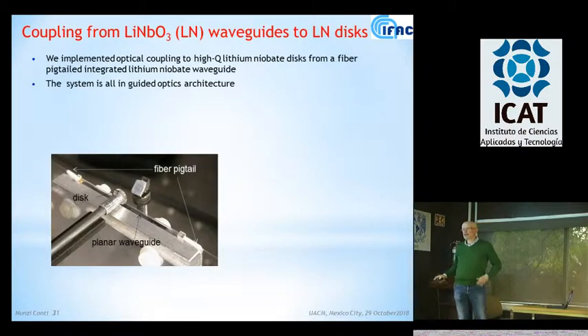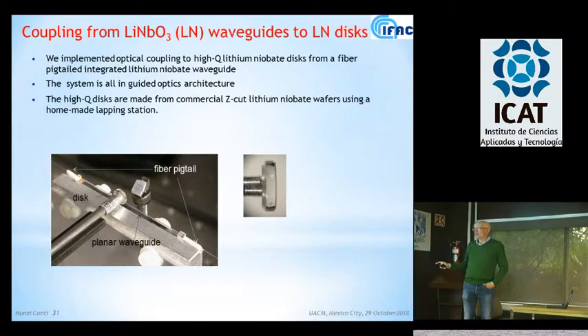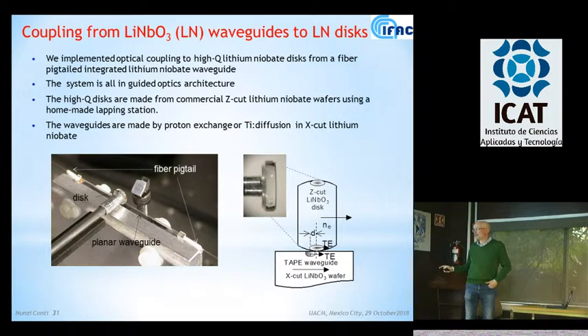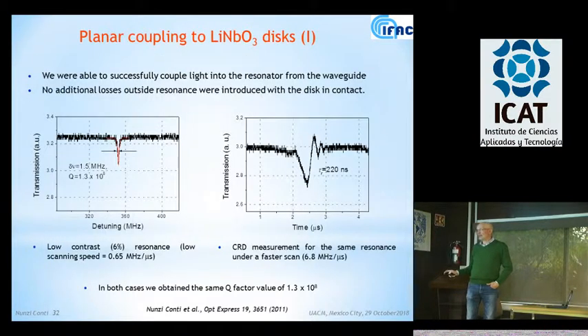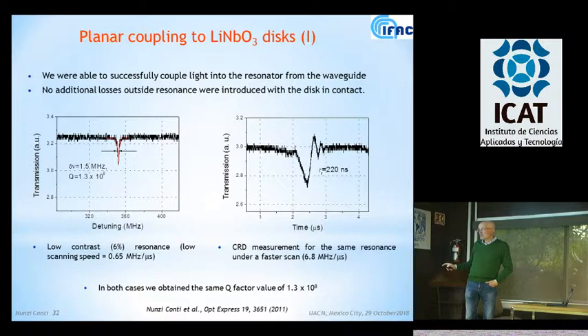And then we worked, as I said, with lithium niobate, because basically we demonstrated that we can couple light from a lithium niobate waveguide to a lithium niobate disc. And of course this was very important for optoelectronic oscillators because of the optoelectronic properties of lithium niobate. We could demonstrate coupling from this proton exchange or titanium waveguide, if we want both polarizations, into high-Q lithium niobate discs. And here is an example of a measurement of the same resonance made by a slow scan and by a fast scan. But you end up, of course, with the same result. Here you can also assess the coupling condition.